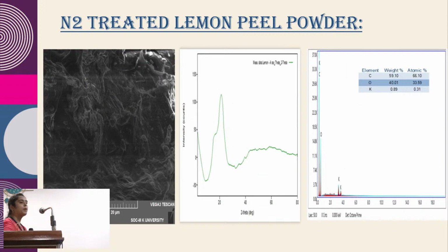Then I prepared my adsorbents in two conditions. One was simply dried and sieved. The other was ground particles that I treated in an N2 atmosphere, mainly for future applications as a fertilizer. The N2-treated lemon peel also shows a highly asymmetrical structure and a highly amorphous region. As I mentioned above, amorphous character is the main property, and therefore the lemon peel adsorbents have high adsorption efficiency.